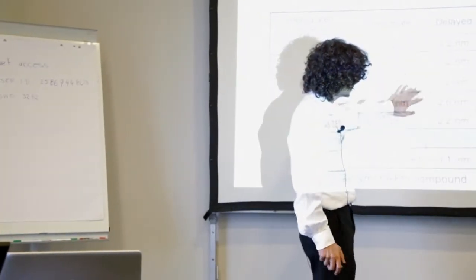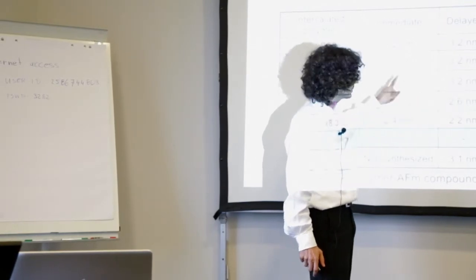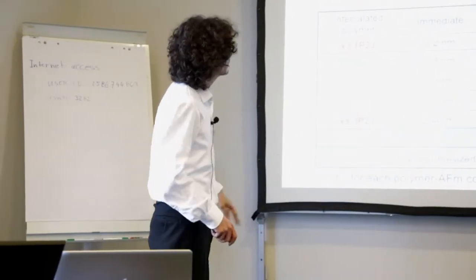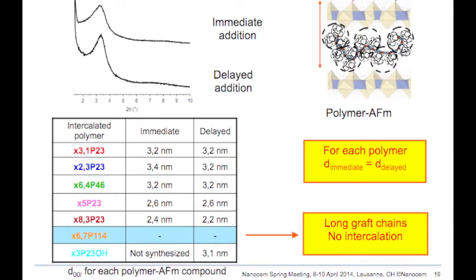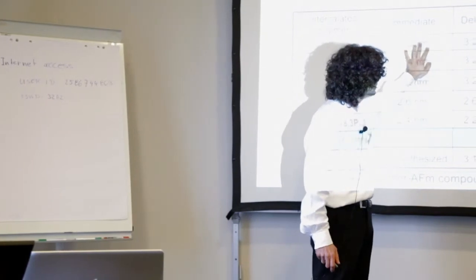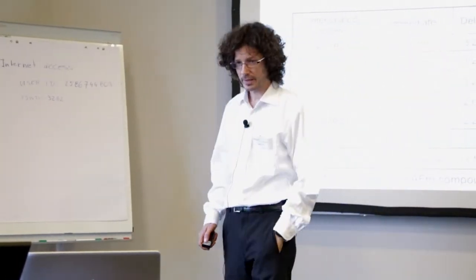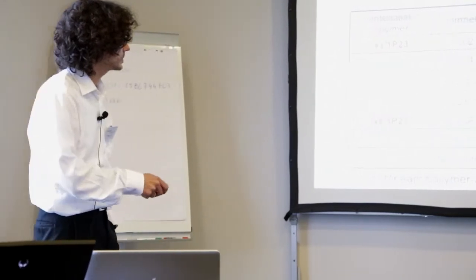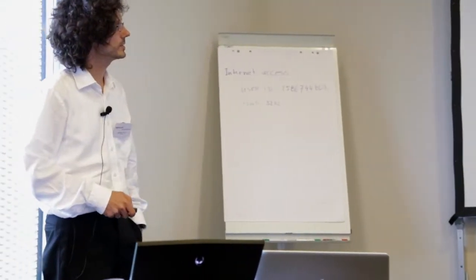The next important one, the values here actually, this is an early analysis of experiments which were not fully adequate as we were just measuring the harmonic of the main peak. But nevertheless, what we find, again, for immediate and delayed addition is that the spectrum is giving a basal spacing harmonic peak at equivalent distances, whether in immediate or delayed addition, and that the large side chains, as also reported by Professor Planck, did not lead to intercalation.